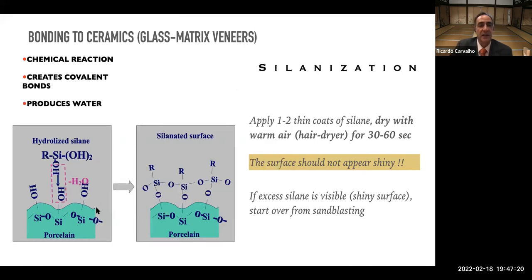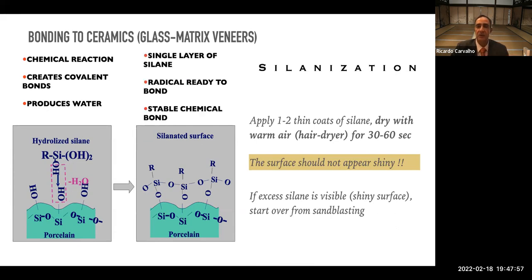This is just a diagram explaining how the silanization happens. It's a chemical reaction that creates a covalent bond between silica on the porcelain surface and the silane. And then, of course, this radical is the radical that will bond to the resin matrix. What is really important is that for every molecule of silanization, there is a production of one molecule of water. So the silanization process itself produces water on the surface. And that water, along with the solvent that is present in the silane solution, must evaporate from the surface in order to allow a proper chemical reaction of silanization. And that's why the time allowed after silanization is really important, and we're going to discuss that as well.